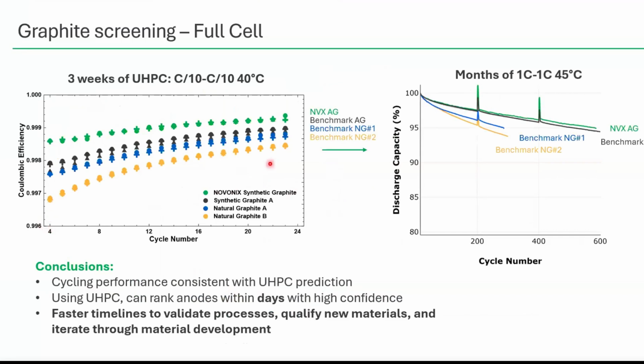This early ranking that we can get, again, this is about a couple weeks of cycling, but you can just look at a few cycles in a matter of days and then predict this order of performance that's going to happen months down the road in normal cycling on a traditional piece of equipment. This allows us to get places much faster and not just predict a ranking of how something's going to perform. There's a lot of insight here that may actually allow us to quantitatively predict things.